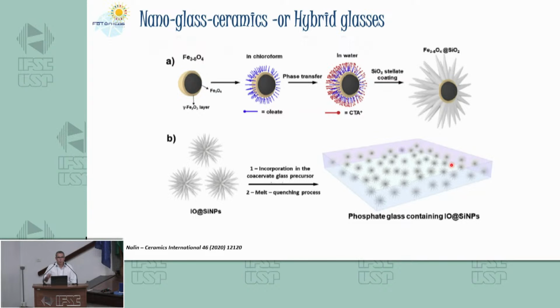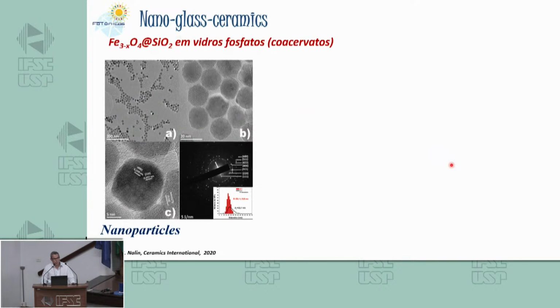So one way is to produce magnetic nanoparticles, in this case iron oxide, cover the particle with a shell, for example silica, and then redisperse these nanoparticles into a glass composition. And then if no ion goes into the glass, we can achieve transparent glass in the visible with magnetic nanoparticles inside the glass. Okay, so this is what we did.